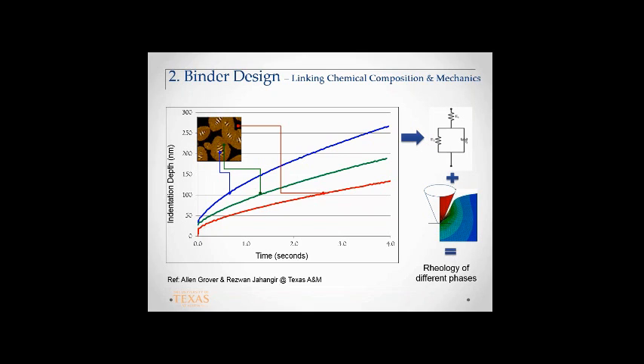So you do these experiments, you get these creep properties, and then you use the geometry that you get from an AFM image, you know the material properties, you assign those properties, and run a simple tension test. And when you do that, what you see is that when you apply a far field stress, you get local hot spots. You see those red areas? Those are hot spots where even if you have a unit stress here, the local stress is about 3 to 5 times higher compared to the far field stress. So you get a 3x to 5x amplification at these hot spots, and that's where we think damage occurs.